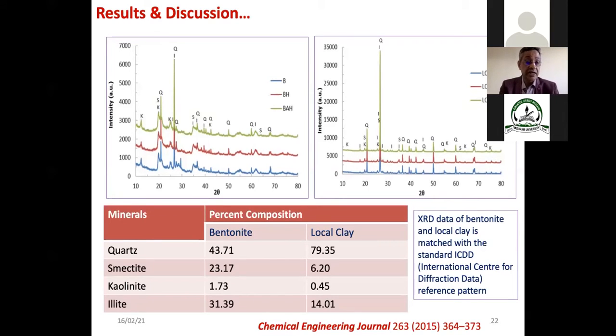The XRD data is showing that the two clay materials, bentonite and the local clay, have quartz content of around 43.71. This local clay is having more quartz compared to the bentonite, as I mentioned. It is 79.35. Smectite is 23 and 6.20. Kaolinite is 1.73 and 0.45. Illite is 31.39 and 14.01. So the illite content is more with the bentonite.